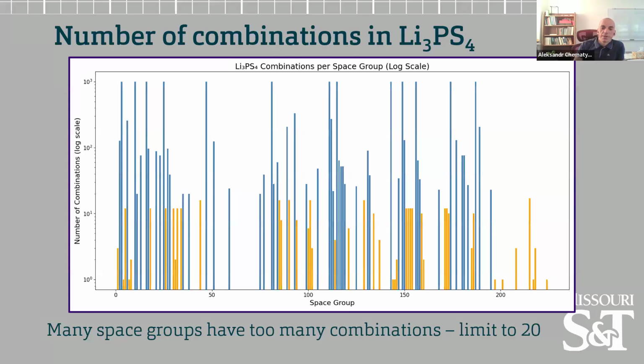And again, one may argue that as I go from left to right here, this is the number of the space group, I'm going to increase the degree of symmetry of the system. As I go to the higher symmetry of the system, I will have fewer degrees of freedom. But at least in principle, I still should be able to find any structures in the space group if I'm looking at the space group P1, which of course doesn't have any symmetry. Of course, in that case, I don't get any benefit of symmetry reduction, which means that I might wander in the phase space forever and not find anything useful.